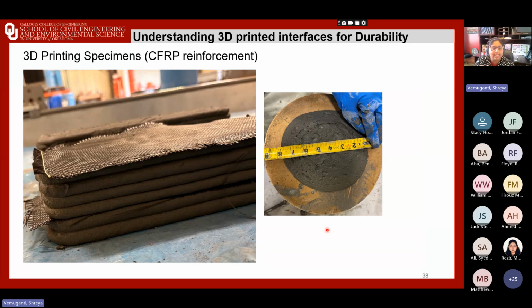In this slide, you're seeing the CFRP reinforcement, which in the Ashby chart, if you remember, is still a composite material, but it's carbon fiber. So glass fiber, carbon fiber, we've studied both these materials. Carbon fiber, if you again go back to the Ashby chart, is much stronger than glass fiber. So the hypothesis that we thought was maybe carbon fiber is more resistant to these aggressive environments and maybe less vulnerable compared to the GFRP. We also saw in the pilot study that carbon fiber didn't necessarily have too much degradation when compared to glass fiber.